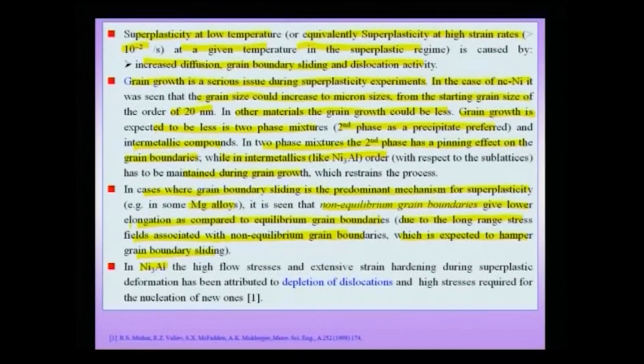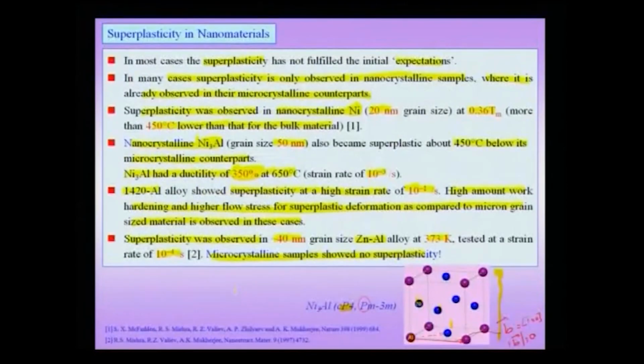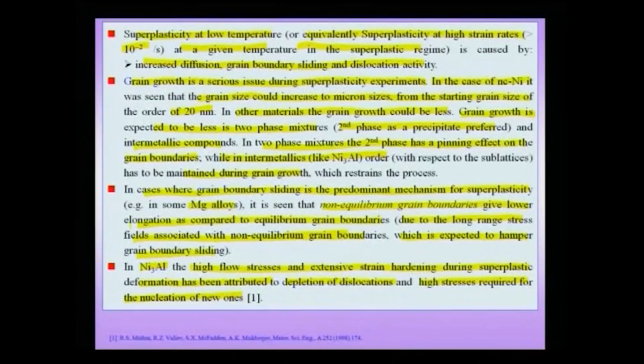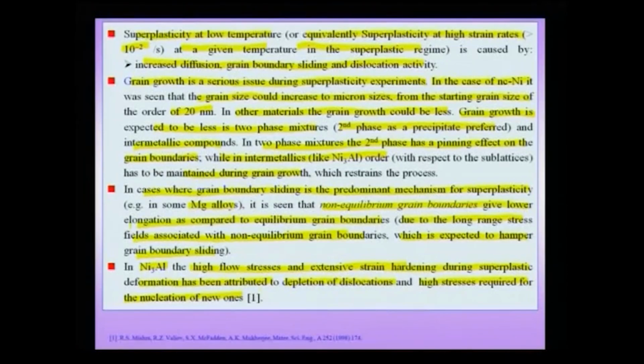In the case of Ni3Al, the high flow stress and extensive strain hardening during superplastic deformation has been attributed to depletion of dislocations and high stresses required for nucleation of new ones. So, we noticed when we talked about the Ni3Al structure and its superplastic forming, that you have superplastic deformation of a 50 nanometer grain size sample. It is observed here that a high flow stress is observed, and additionally there is extensive strain hardening during superplastic deformation. That means with progress in superplastic deformation the stress has to be increased, that means the forming cannot take place at constant stress, and this is attributed to depletion of dislocations and high stresses required for nucleation of new ones. So, this has been the reason why Ni3Al is difficult to form.